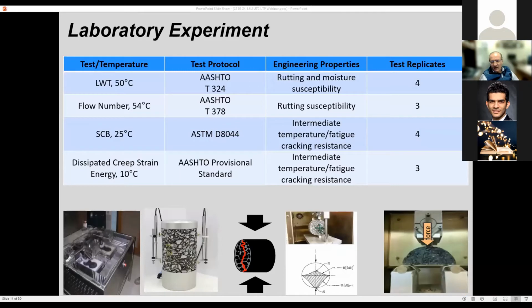Now we go back to the laboratory because the objective was, is there a lab test that can rank those distresses at high temperature, intermediate temperature specifically? So at the time when the study started, we had an LWT for high temperature, flow number for high temperature as well. And we looked at 2 tests for intermediate temperature cracking, which is SCB as per ASTM D8044 and the dissipated creep strain energy test.